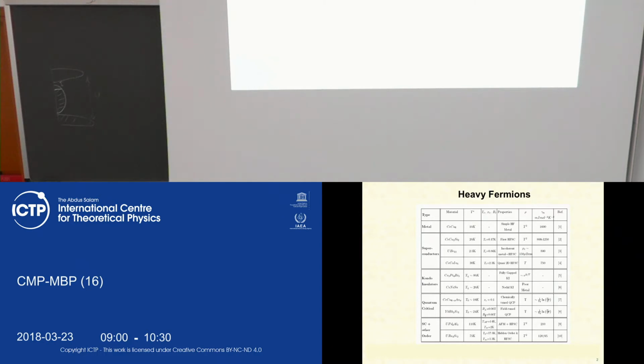Therefore, if the density of carriers is fixed, the Fermi momentum is proportional to the density to the power 1/3, sorry, and if we write down the Fermi energy as p squared divided by the effective mass, which is a few thousand times the mass of the electron, we get that the Fermi energy is also a small number, of the order of a few Kelvin. Contrast this to the Fermi energy of a conventional metal, which is of the order of a few 1,000 or 10,000 Kelvin.